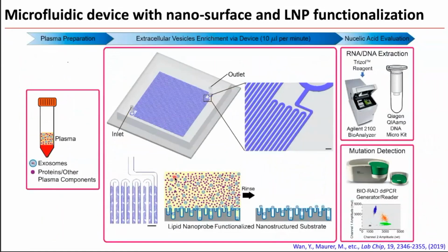So one outcome of this study, as a follow-up study, we tried to make this principle into a microfluidic device and also use the more sensitive digital droplet PCR for the detection. As you can see in this diagram, instead of using a 2-component system, we basically conjugate the lipid nanoprobe on the surface of a microfluidic device. To improve the capture efficiency for this particular device, we generated a nanostructured substrate and then conjugated those lipid nanoprobes. And again, we use off-chip digital droplet PCR as a more sensitive detection mechanism.